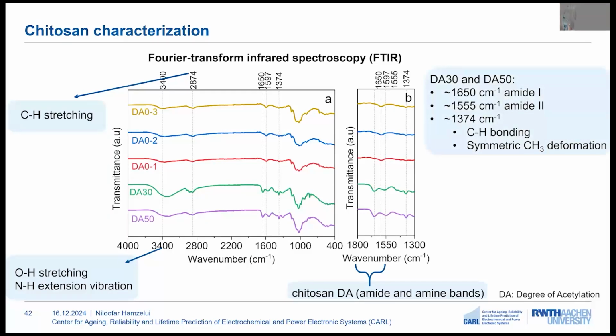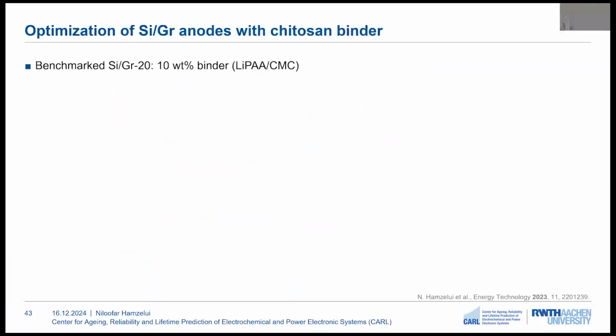So for the chitosan binders with higher degree of acetylation, we can see amide 1 and amide 2 bands, and also the CH bending and symmetrical CH3 deformation in this region, which we are not seeing for the chitosan with DA0, as it is expected. And for the DA0 samples at 1,600, we are seeing the primary amine groups.